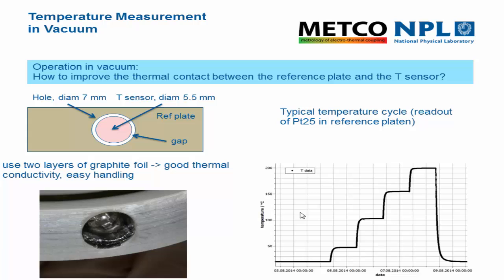And so I think, Guido, you've been evaluating the thermal time constant for these temperature steps, so that they can make sure that the sample temperature corresponds with the measured temperature at the time of the test. There are some important things around thermal contact. One of the things that we want to try and achieve is to get good thermal contact between the sample and whatever it is that's controlling the temperature, so the source of the heat.